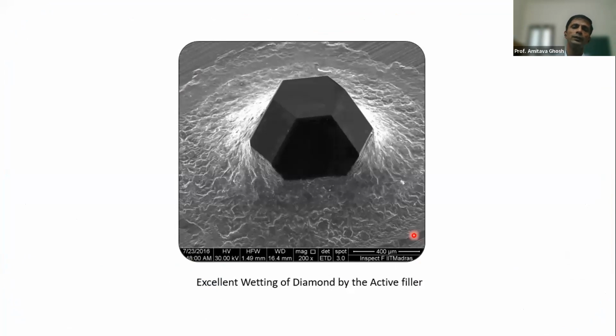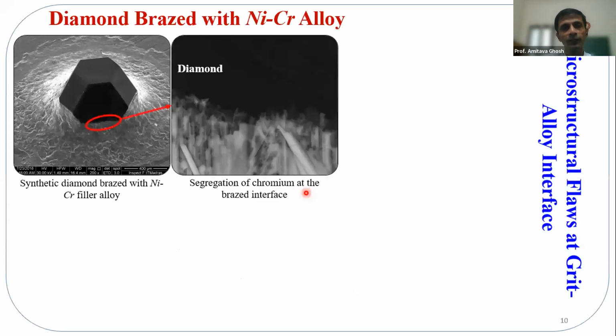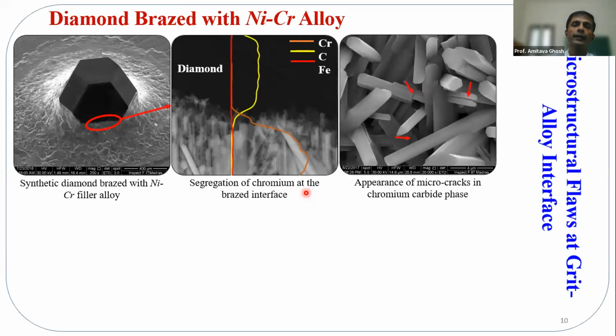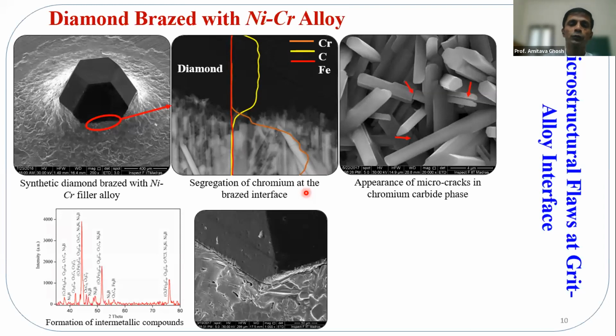And now, if you see how the diamond looks after the brazing, this nickel chromium alloy nicely wets the diamond surface. Apparently, it's an excellent wetting, and the joint looks to be very, very sound, even under a not so high resolution scanning electron microscopy. But if we really look into the joint critically, especially at the interface, we find that there are chances of formation of micro cracks. These micro cracks are generally very, very detrimental.